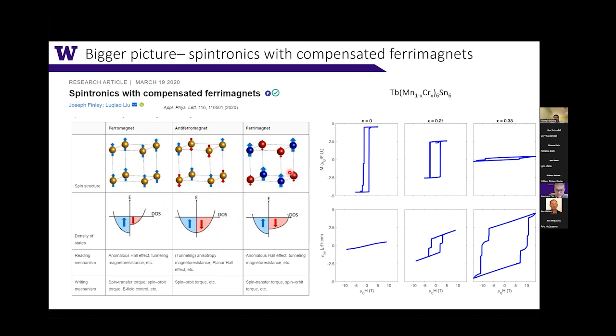So the compensated ferrimagnet offers a balance where you can create a zero net magnetization state by compensating two kinds of moments. At the same time, you also have a large anomalous Hall effect to read out. And perhaps there are ways you can switch the magnetization on and off, just like what we were seeing with the temperature, and reduce the magnetization to zero so that the stray field doesn't affect the next memory cell. In this sense, this chromium-doped terbium manganese 166 fits this picture almost perfectly, where you have zero net magnetization with a very large anomalous Hall effect.